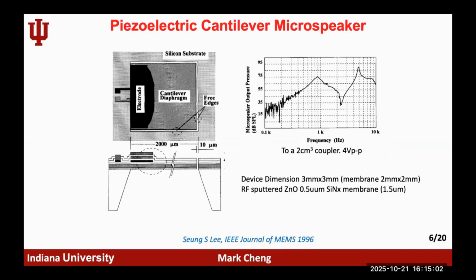Okay, so I'm going to give some history for this field. The first piezoelectric micro speaker you probably find goes back to 1996, back to Berkeley, where Professor Lee used the cantilever design. At that time PZT and aluminum nitride didn't really exist, so they used sputtered zinc oxide as the piezoelectric material. They put it on the edge and used the cantilever structure to amplify that vibration. Because this cantilever needs to vibrate, they have to cut and release the structure as a cantilever, which is called the free edges, and this is the response they got a couple of years later.